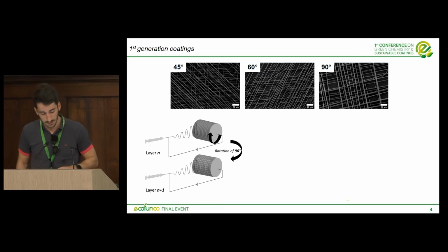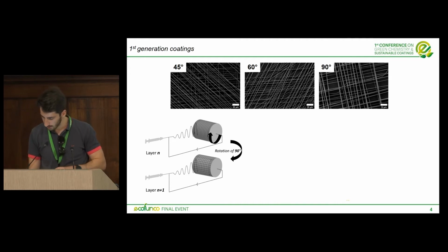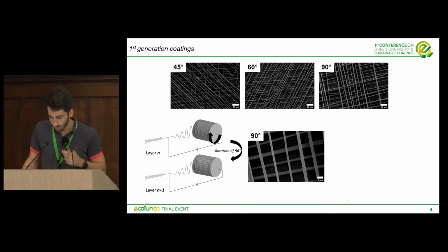that consisted simply in rotating the substrate, in this case an aluminum foil, by a specific angle after collecting a layer of fibers. For better reproducibility and aiming to produce coatings with more than 4 layers, we focused our research on the 90 degrees orientation. So we are talking about fibers of different layers that are perpendicular to each other.